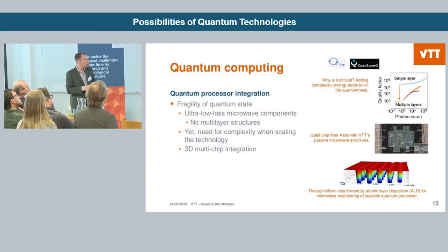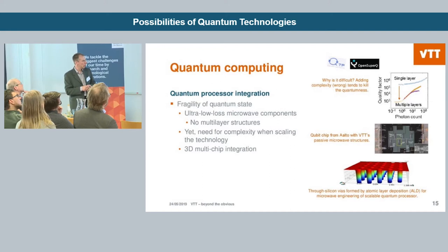This shows, for example, a microwave resonator that is a part of a practical superconducting quantum computer. Here is this plain resonator structure. The quality factor tells how good it is in terms of losses, so that it isn't coupled to a lossy environment and thus kills the quantum coherence. If you start putting materials that are typically used in IC fabrication, you collapse the quality factor, and then your quantum computer doesn't work or works very poorly. So that's why it's very important how you do it.